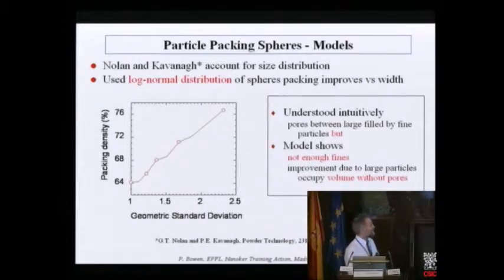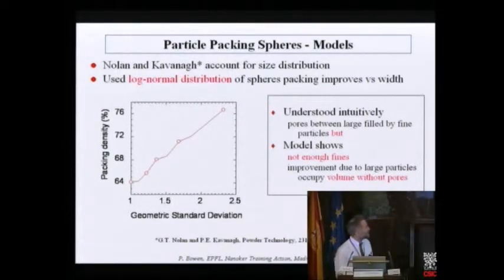This was understood intuitively: small particles came in and filled the gaps between the big particles. But in fact, the modeling showed, which is why I also like a theoretical approach, that there are not enough fine particles in the log-normal distribution to fill the gaps between the big ones. What you have in these very broad size distributions, which means you have several orders of magnitude difference in the particle sizes, is one or two very, very big particles which have no porosity. So you have areas like that, which is not necessarily good if you want a nice homogeneous microstructure.